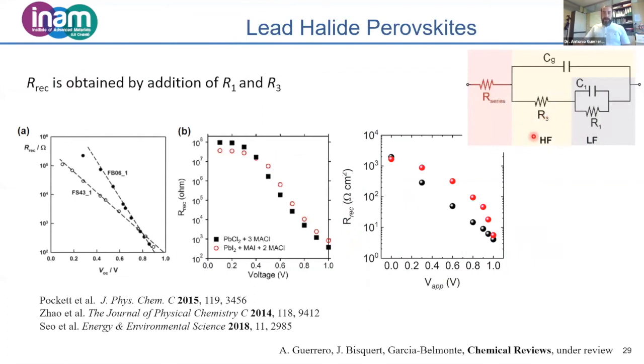Okay, so if we start with the more or less validated equivalent circuit, this is the equivalent circuit that we believe best represents the physical processes that occur in a perovskite solar cell under illumination when it's working. So we see the series resistance, and then we see this RC, this is the high frequency arc that we observe, and this low frequency arc connected to the contacts. The main idea, and I will explain this in more detail, is that we can calculate the recombination resistance related to the recombination current that I showed you in the second slide, which is obtained by the addition of the two resistances, the low frequency one and the high frequency one.